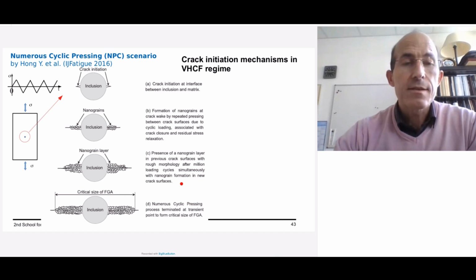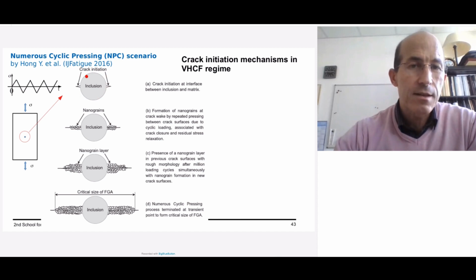A very promising scenario is also proposed by Professor Yushi Hong a few years ago. Around an inclusion, the scenario is very close to the Sakai one, but it explains why there is an optical dark area when there is a part of the cyclic loading under compression. That's why the model is named numerous cyclic pressing, like compression. The phenomenon of optical dark area is not observed where mean stress is high enough to have the cyclic load only in tension.